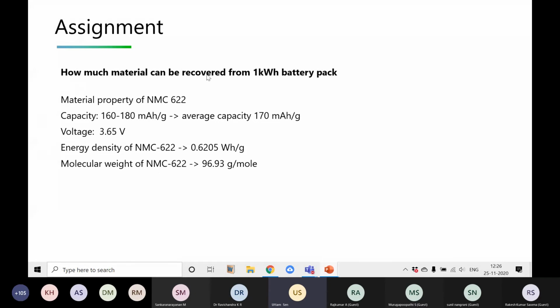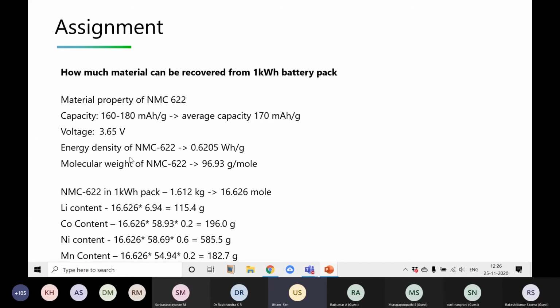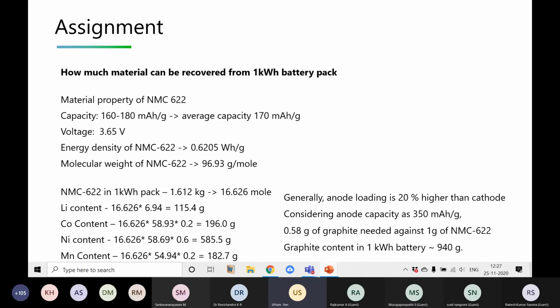Okay, then we can do all the back calculation. You can do the calculation and come up with the numbers: how many moles will be there, and finally how much material we can extract if we recycle a 1 kilowatt hour battery pack which consists of NMC 622 and graphite. Okay, so we can get lithium of around 115 grams, cobalt around 200 grams, and nickel, mostly nickel, around 600 grams, around 180 to 200 grams of manganese, and around 1 kg of graphite. That is what we can get if we recycle 1 kilowatt hour.